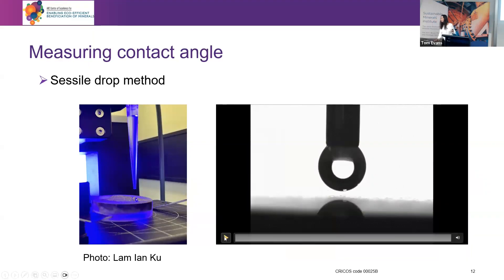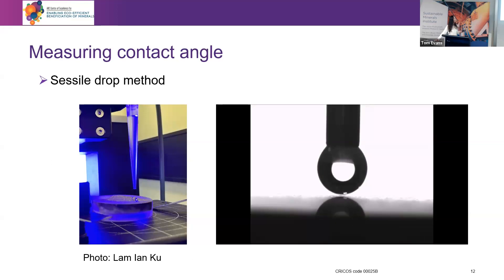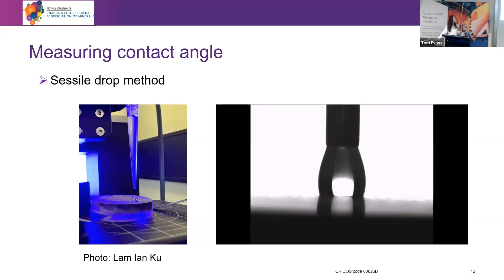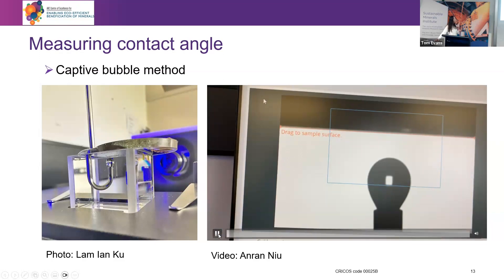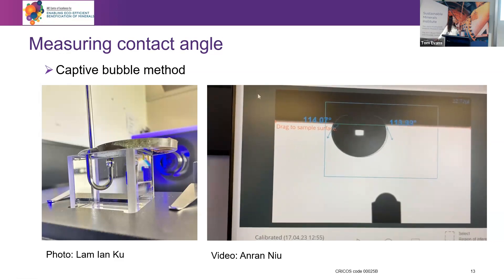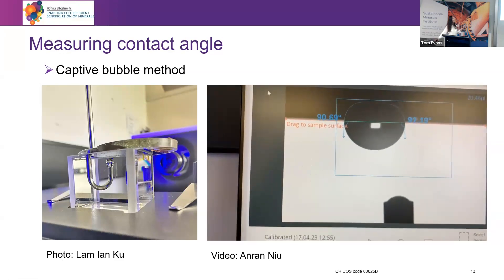We can increase the droplet size until it attaches to the surface, and through this method we can also increase the volume of the liquid droplet and calculate the water advancing contact angle — I'll talk more about this, as it's an important measurement. We can also do the captive bubble method, where we have an air bubble in water and the surface immersed in water, and then we approach the air bubble to the surface and measure the contact angle. This is actually more similar to what happens in a flotation context.